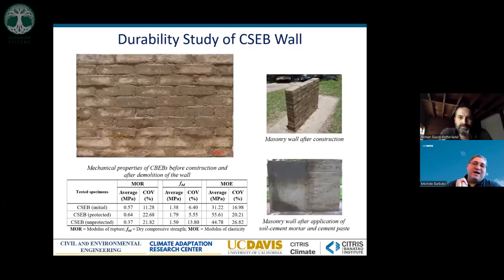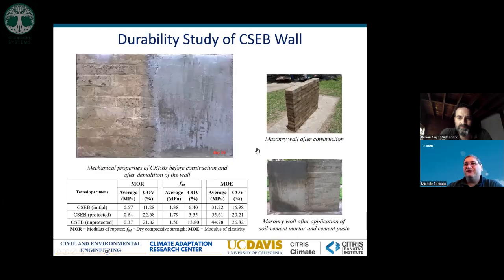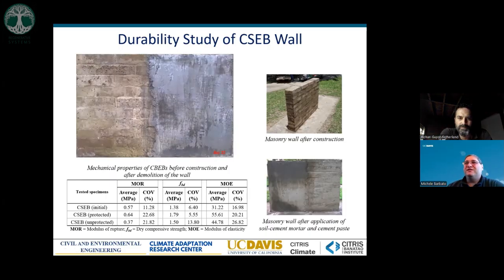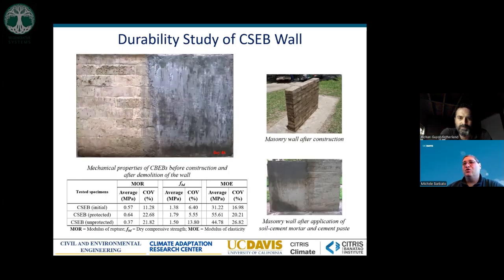The other issue that we had with the wet and humid climate is to ensure the durability. And so what we did was a test. We built a small wall outside of LSU, and we left it there during the summer for about 6 months to see what was happening to the wall. Now, 6 months may seem a short time, but during that period, we had two tropical storms. So quite a lot of rain, quite a lot of loads.